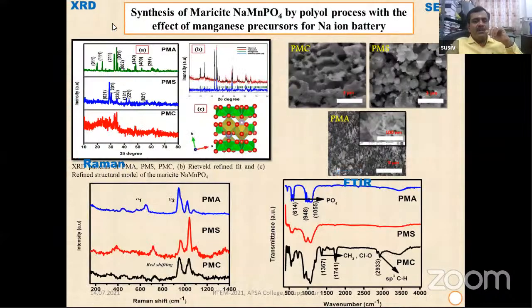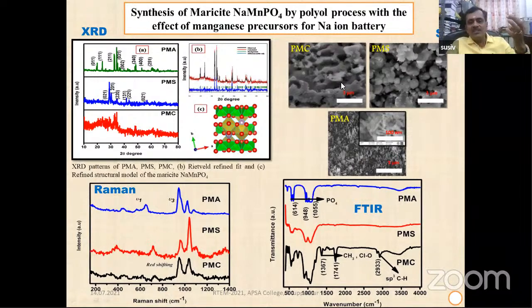For some example, we have prepared the synthesis of maricite NaMnPO4 by making the maricite electrochemically active and participate in the electrochemical reaction by means of a polyol process and with various precursors. We have used several precursors such as manganese acetate, manganese chloride, manganese sulfate. But out of which, using the acetate precursor, it forms NaMnPO4 very well with this structure.